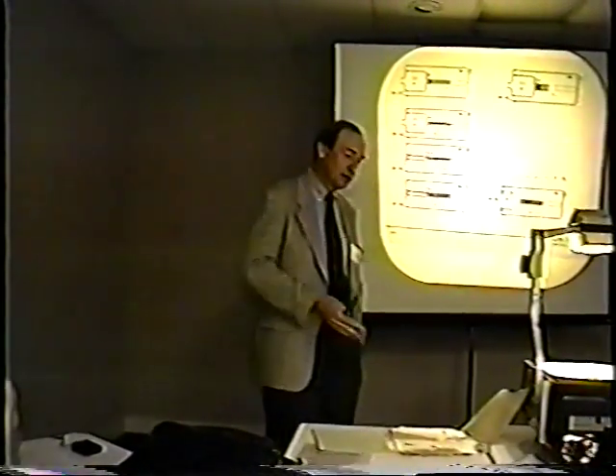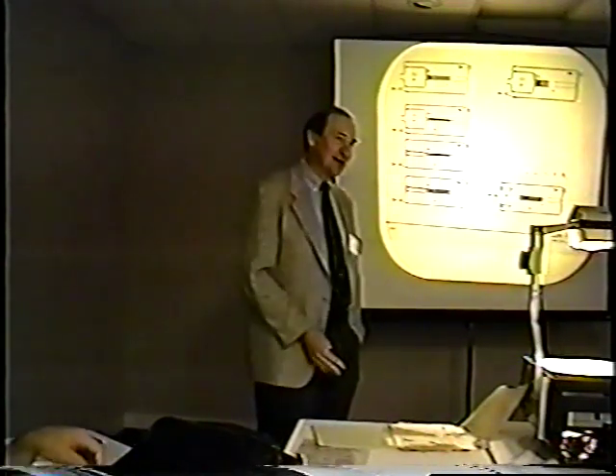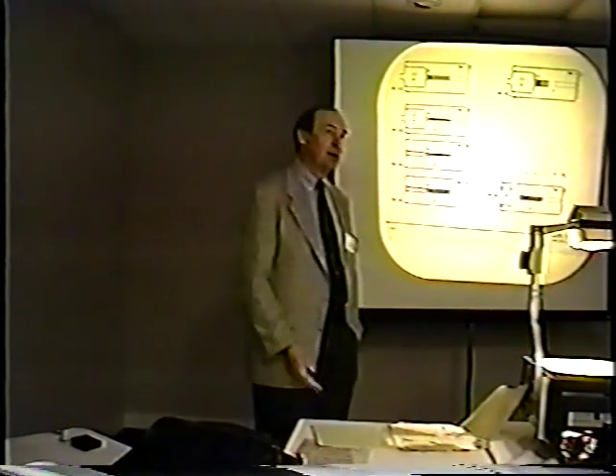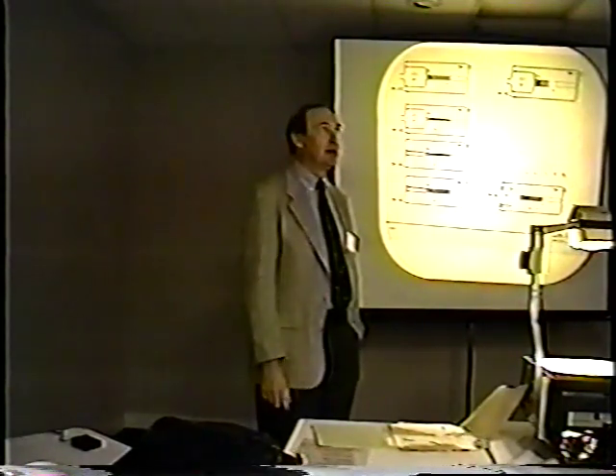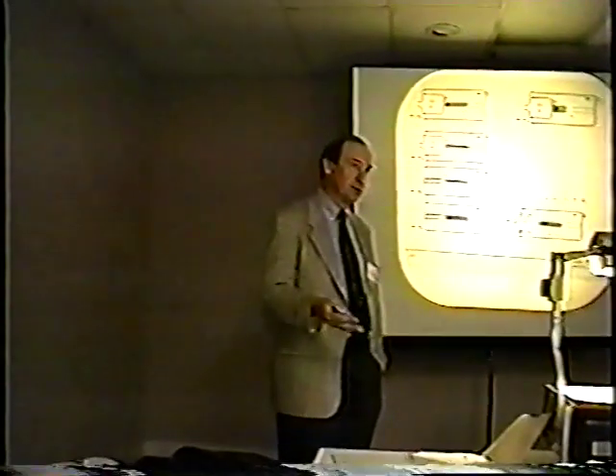The other question is, other than the fact that the NRL seems to be a black hole for cold fusion experiments, why didn't theirs work? I think that was partly due to the fact that we ran out of the good batch of palladium. We had this batch of palladium, we were getting these fantastic results. Everything was very nice. We enticed NRL to come in and try and replicate it, and then we used it all up by the time they started, and we had to send them our sort of second string batch, which gave us those very weak results. And then if you run a couple and the system isn't clean, I think you're going to get zero after that. So you have to clean and hydride.